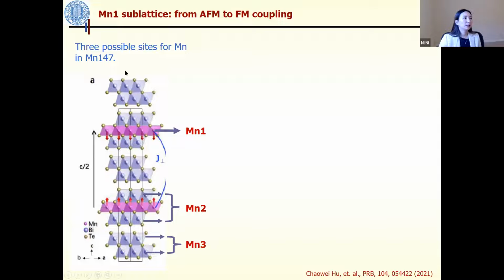So let's take a look at this crystal structure for 147. Compared with the 124, the 124 will have a manganese 1 sublattice and a manganese 2 sublattice. The manganese 2 sublattice arises because of the manganese-bismuth antisites, because manganese goes to the bismuth site in the 124 layer.